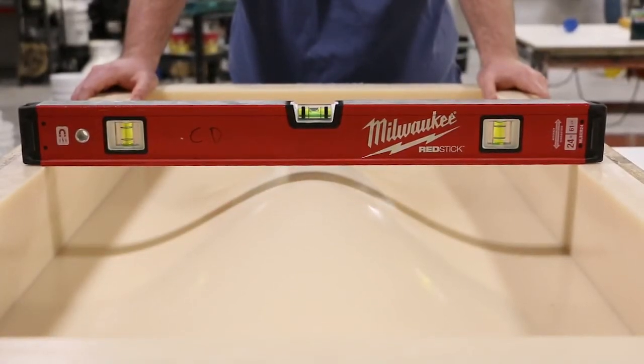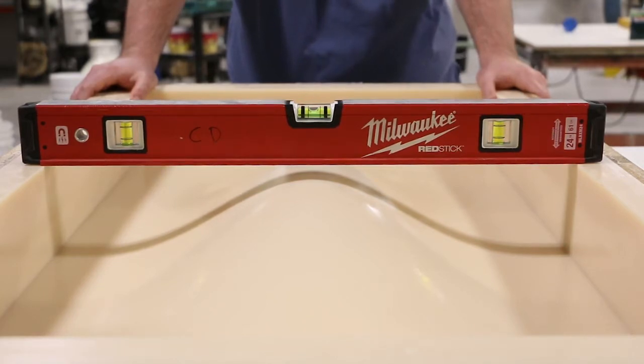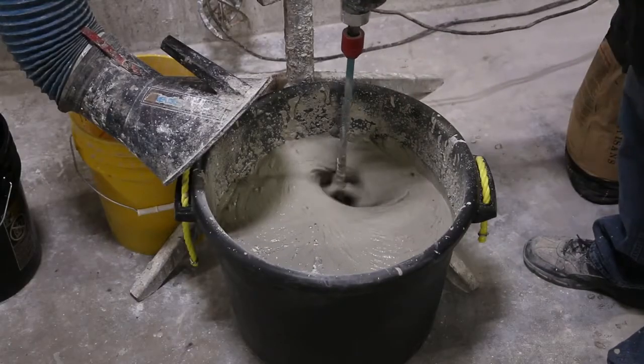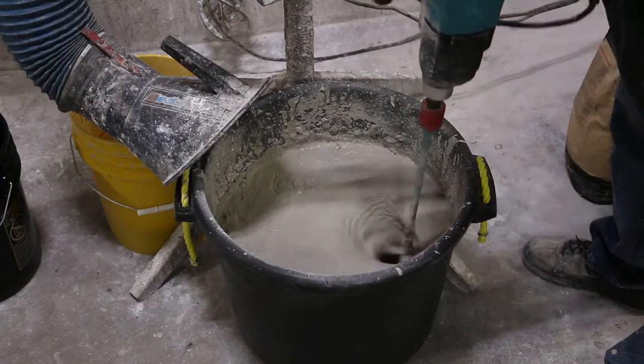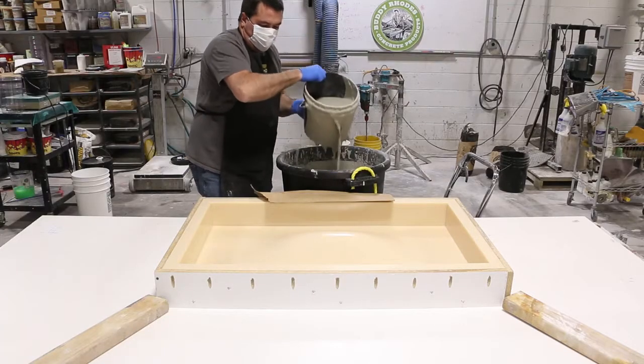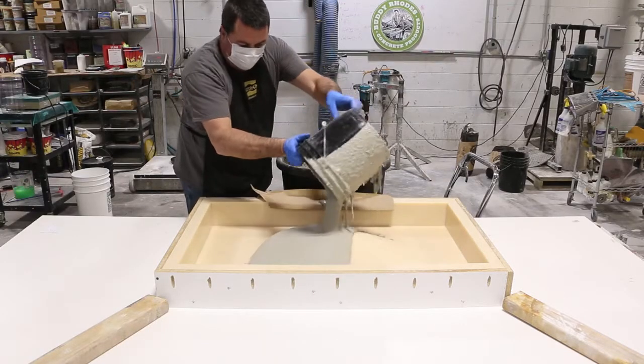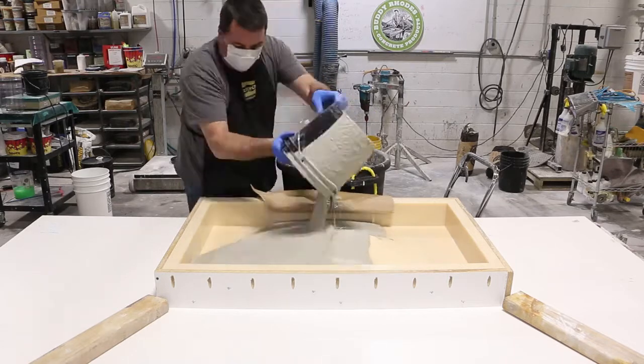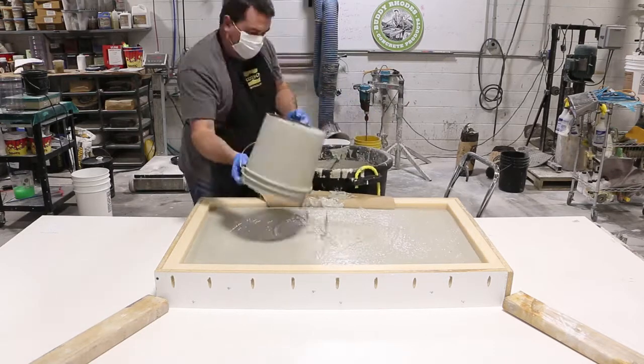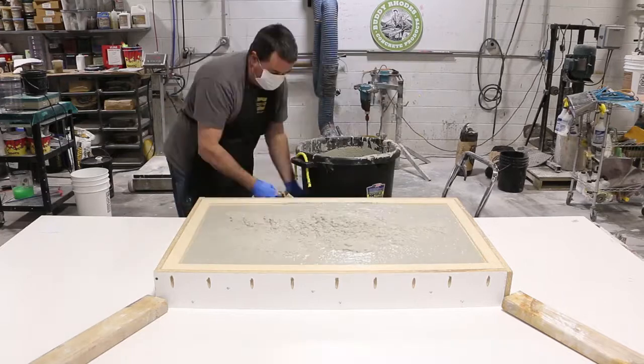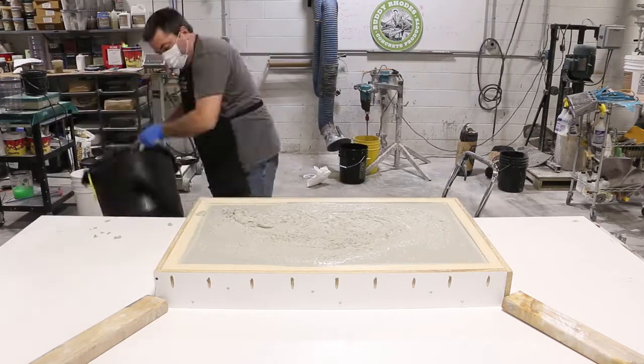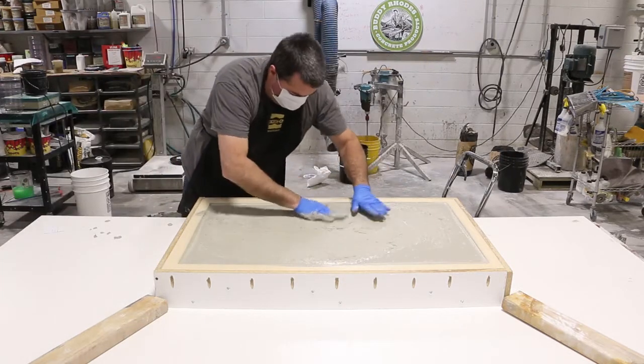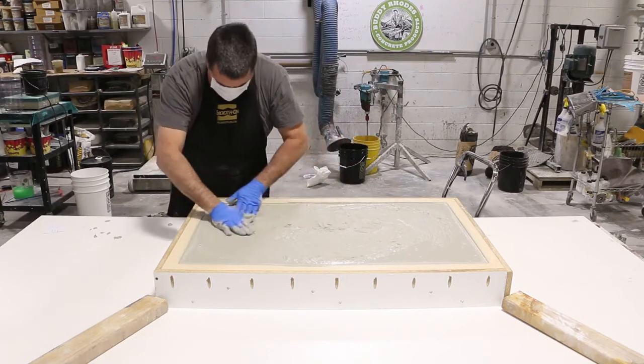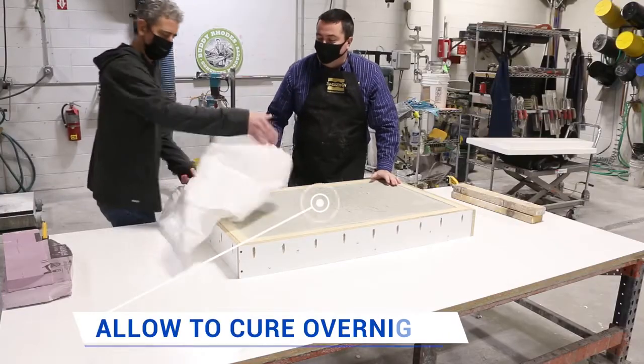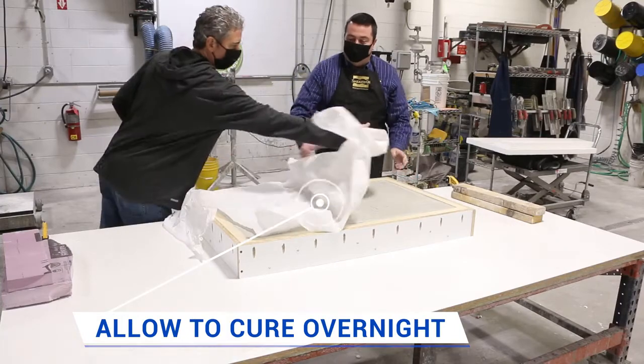In preparation for concrete casting, make sure the mold is positioned level on a flat surface. I mixed a generic self-consolidating concrete mix with some old material I wanted to use up. This will be a sacrificial casting. This is a good idea in order to season the mold and helps to remove mold production release agents and waxes that may be present. These will almost always have a negative result on the first castings with discolorations or spotting. Cover and allow to cure overnight.